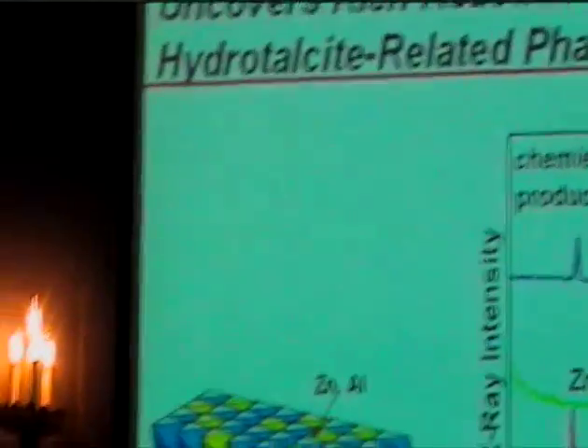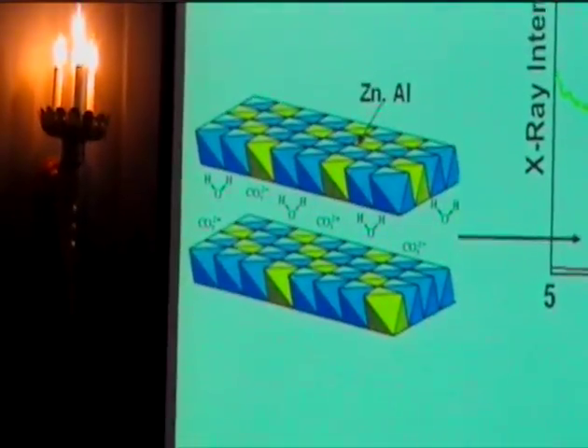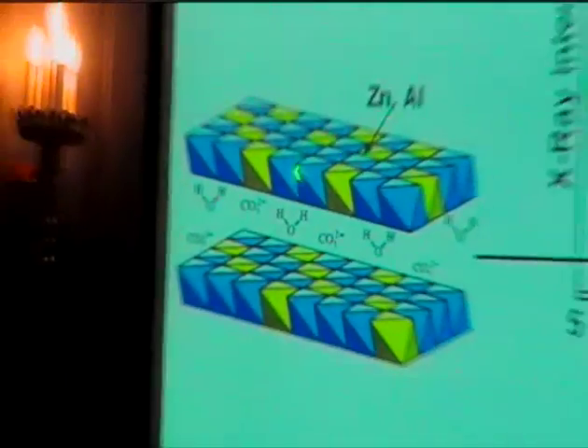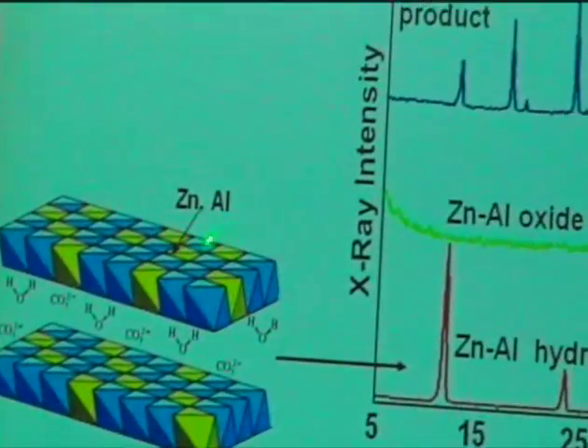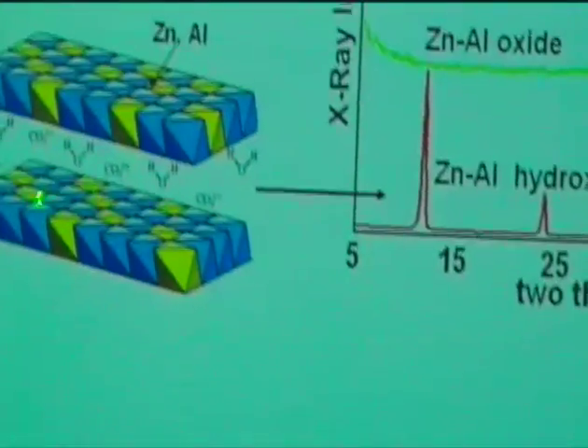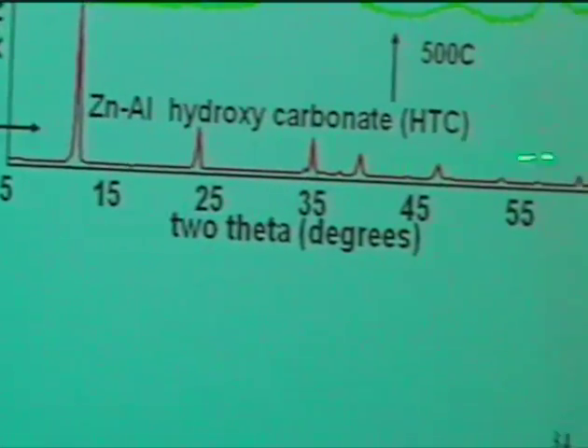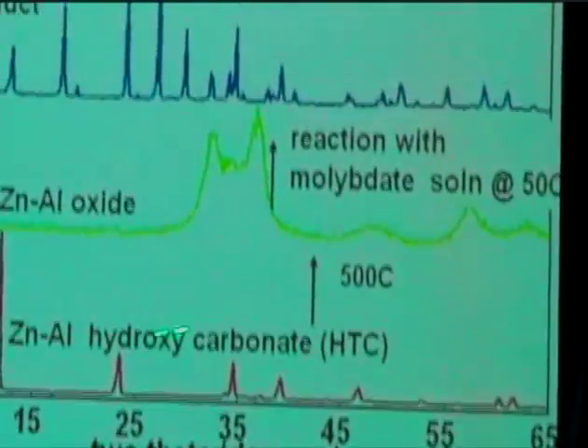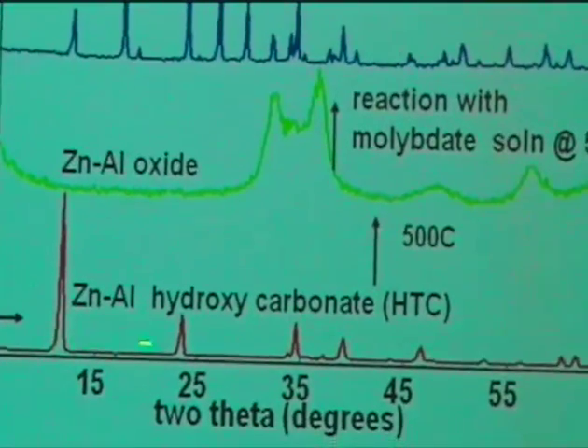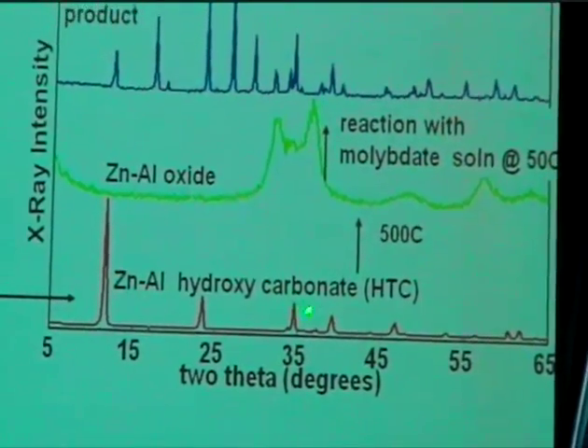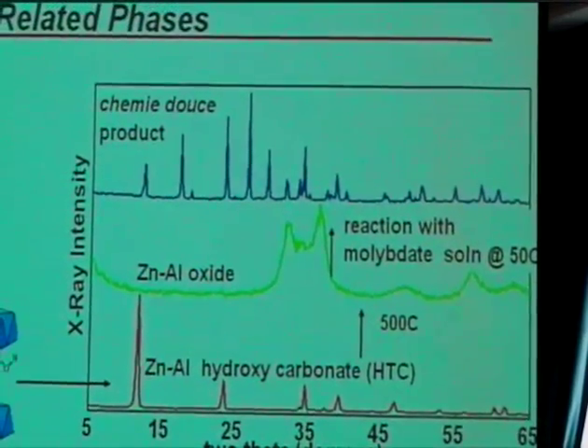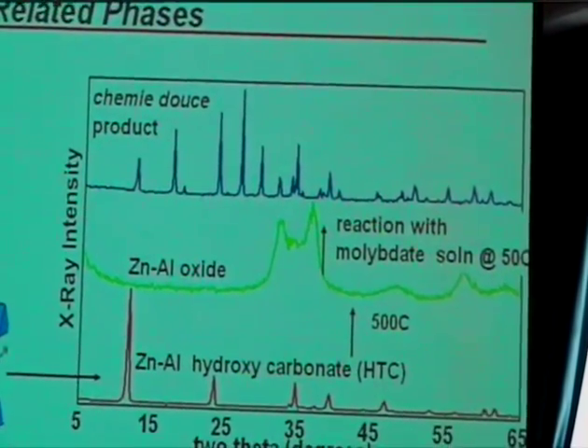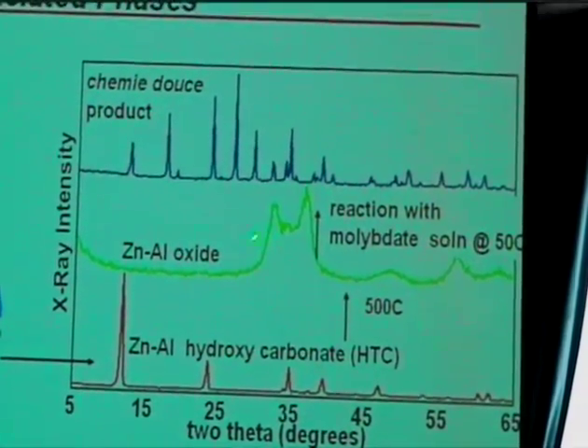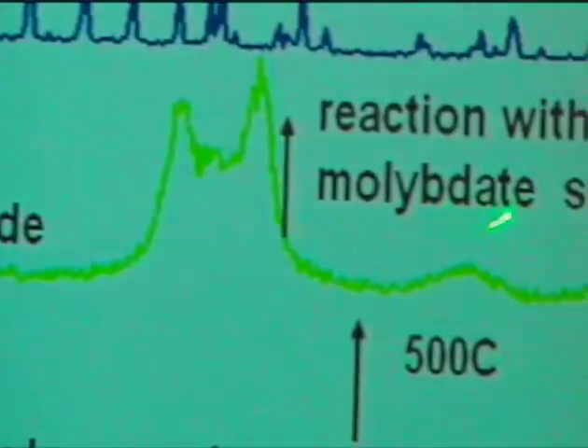So in the course of the work of that summer, we found one interesting thing that really took us off. We wound up actually working with the zinc aluminum hydrotalcite instead of magnesium. And here's an indication of what happens when you do some heating with this. If you take the zinc aluminum hydrotalcite and calcine at 500 degrees, what happens? The carbonate leaves, a lot of this water leaves, and you wind up just making an oxide, a very broad looking oxide. It looks like zinc oxide with a little bit of aluminum substituted into it.